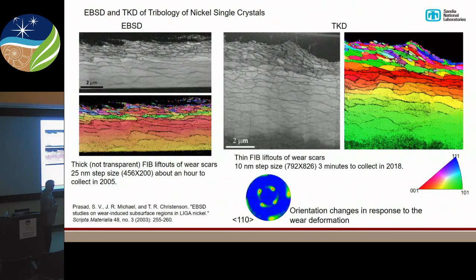And so these new fast detectors really make this transmission mode very useful, and we can push the resolution certainly way down to a few nanometers. And I think it's a really nice development. I would argue that this is better than anything that TEM can ever offer us. I know those are fighting words, I'm sorry. Except for the newest precession diffraction, the NanoMEGAS, that sort of thing. We've had long technical discussions about what they measure versus what we measure with EBSD. And the two are quite different, and you see differences in the patterns, or differences in the maps that you get. But certainly being able to do this all in one tool is really nice.